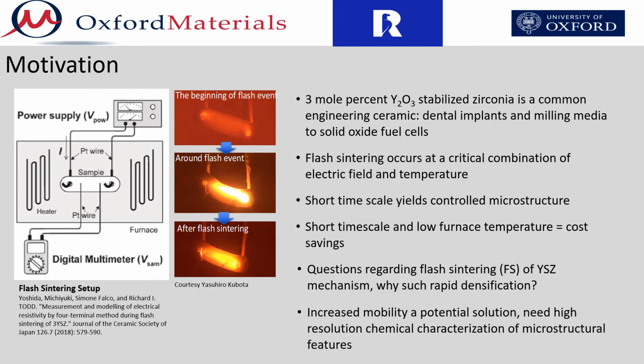Because flash sintering occurs on such a small time scale, there also exists a possibility for fine microstructural control when using flash sintering. Although flash sintering shows plenty of promise when applied to YSZ, questions still remain regarding the fundamental mechanism causing such a rapid sintering rate. In order to answer these questions, high-resolution chemical characterization of flash-sintered and conventionally sintered YSZ is needed, and atom probe tomography is an attractive technique for doing so.